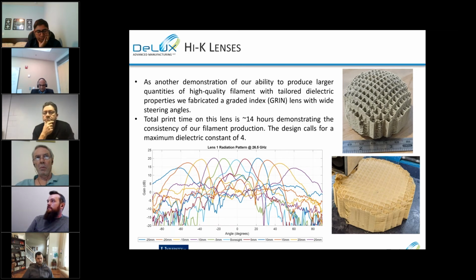Here is a lens that we made off of a flat back feed plane. We're able to get plus or minus 55 degrees of steering and beam forming. We're working to drive that out as far as 70 degrees, which we're only able to do by tailoring the dielectric constant of our feedstock when we're printing. This has a wide range of applications. One of the products that we have in small scale production at this point is radar detection systems. We have passive systems that you can set out, and it will use the passive lens to allow you to know directionality and intensity with which someone is looking at you with an RF signal over a broad band of frequencies.